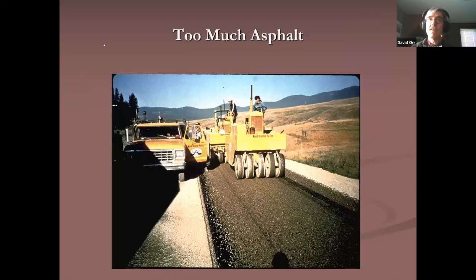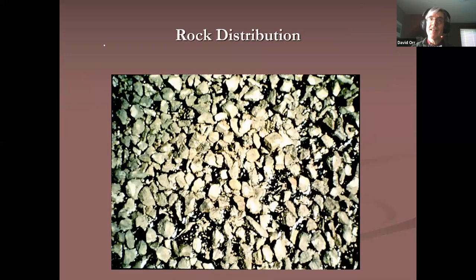In terms of asphalt application, if you put down too much, you're gonna get bleeding. That's not good. What you really wanna see with the rocks is a little bit of asphalt sticking up, but not too much. What happens if you get too little asphalt? Let's see if somebody answers this one. Stone loss, and if you lose stone, that means you're back to having emulsion and you're gonna have bleeding. Great irony: if too much or too little of either emulsion or stone, you wind up with bleeding, because the stones don't adhere.